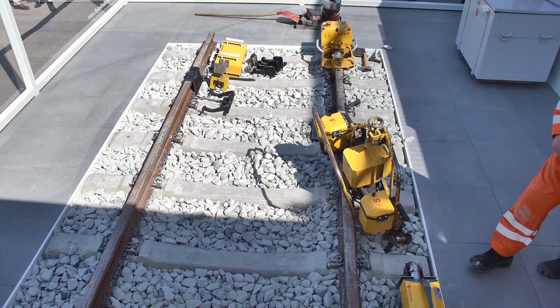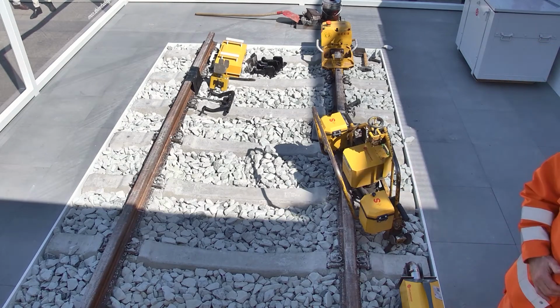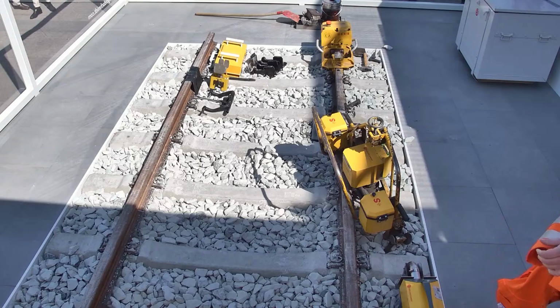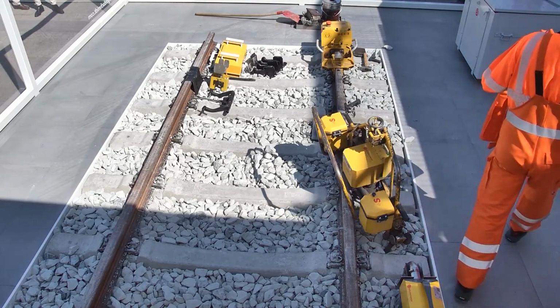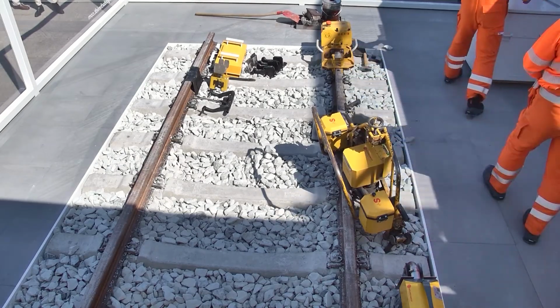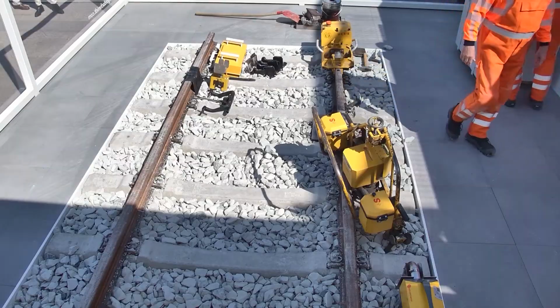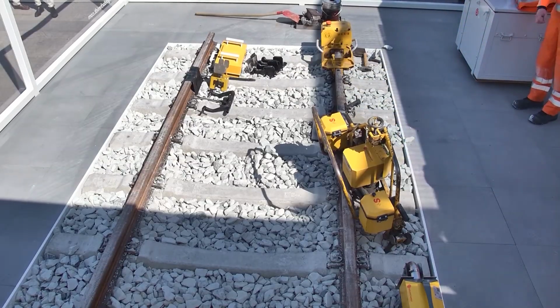And then finally, after performing the grind and after performing the weld, we also have the tools to inspect either with the rail straight for geometry, and also with the track scan for ultrasonic inspection of the weld. So all the tools that are necessary to perform a weld can be found and acquired here from us.